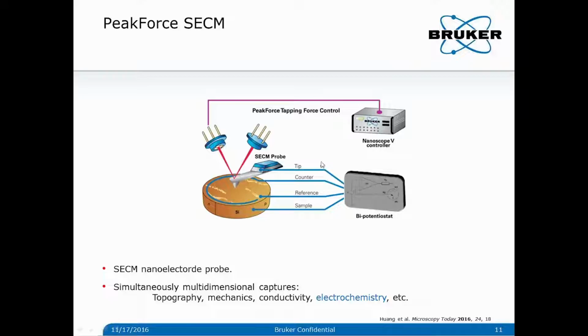You can see that in this bipotentiostat configuration, we have 4 electrodes, and the tip and the sample are both working electrodes sharing the same counter and reference electrodes. So combining with AFM, especially with the peak force tapping technology, peak force SECM is capable of capturing simultaneously multimodal information such as topography, mechanics, conductivity, and electrochemistry. And because it's using a nanoelectrode, it allows electrochemical resolution below 100 nanometers, which is an order of magnitude higher than conventional SECM using a micro tip.